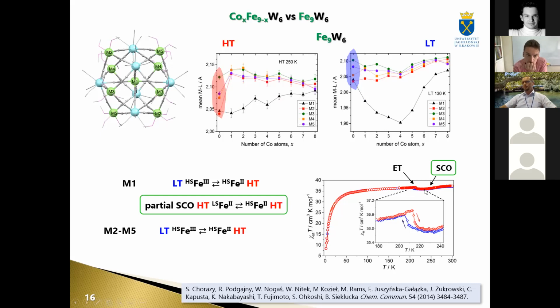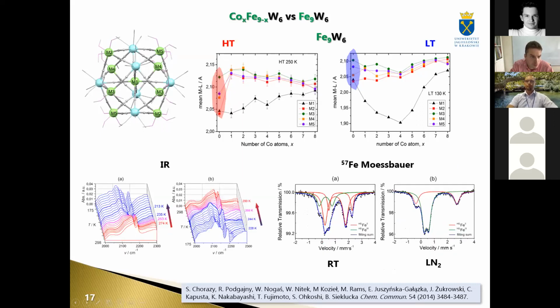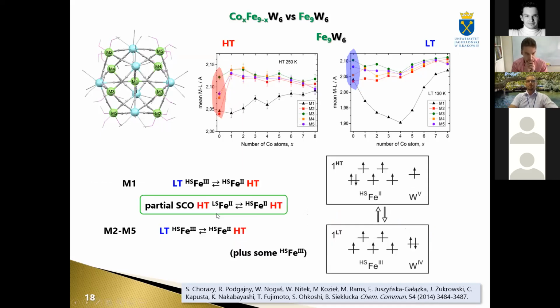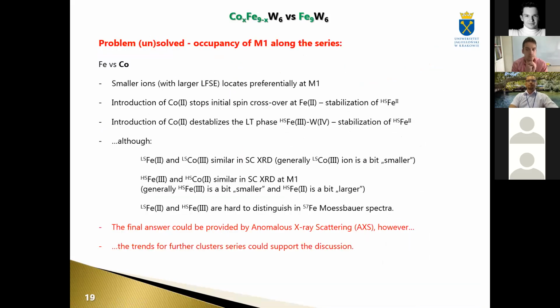Then this spin crossover induces somehow the electron transfer behavior, and this is the way we understand it. All this is in agreement also with the structural data shown here in low temperature. So here we have domination of iron-3 high spin and cobalt-2 high spin, and here we have in high temperature domination of iron-2 and cobalt-2. We also use the temperature variable IR spectroscopy and Mossbauer spectroscopy to show the changes in this compound. They are a bit different compared to the trimetallic ones with phase transition. Okay, so for this moment, I can say the problem is unsolved.